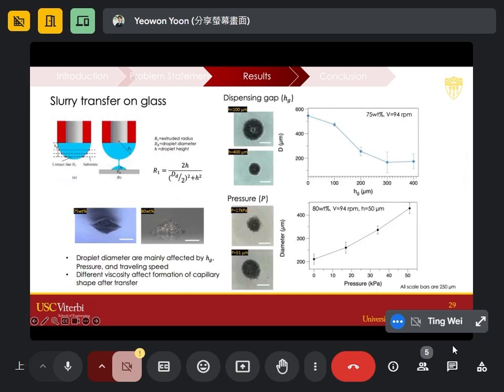Okay, so these were the slurry transfer on the glass. Basically the bottom line here is, if you increase the distance between the plunger and the substrate, we get a minimized transfer, because the contact happens based on the area of your surface, the area you touch the substrate.